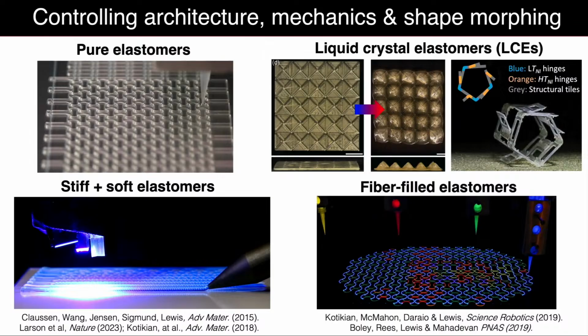And then I'll go to some liquid crystal elastomers. This work was actually motivated in part by that earlier work that I showed with that shape-morphing flower, which was a hydrogel with cellulose fibrils, and some more recent work where we used short glass fibers to create these three-dimensional structures that morphed from 2D to 3D shapes by controlling the alignment of these fibers. That led us to start thinking about whether, even at a molecular scale, we could encode alignment using printing, and what that might end up resulting in terms of shape-morphing capabilities.